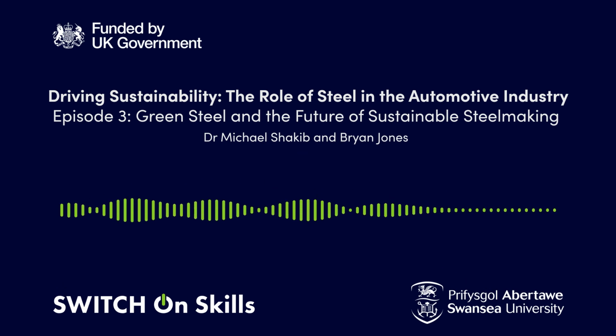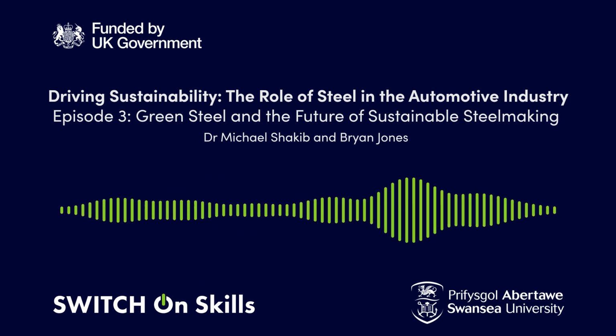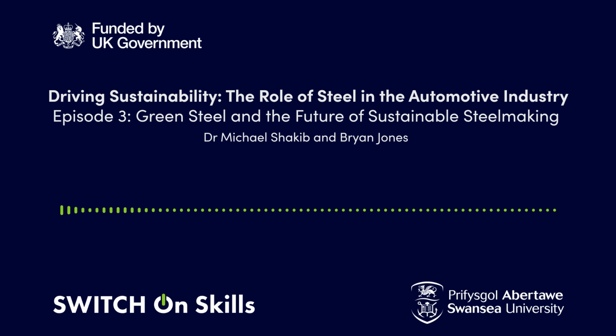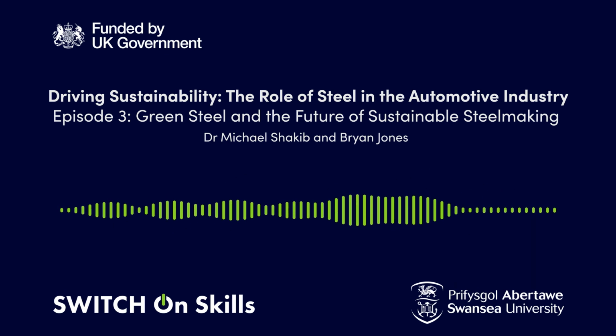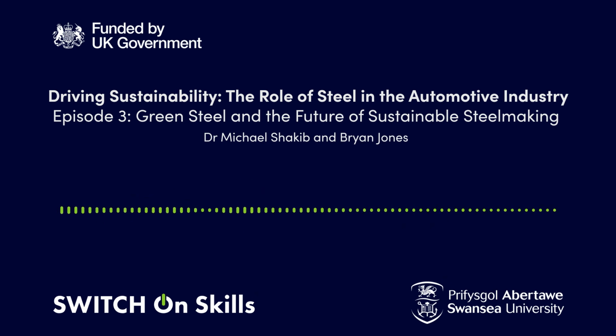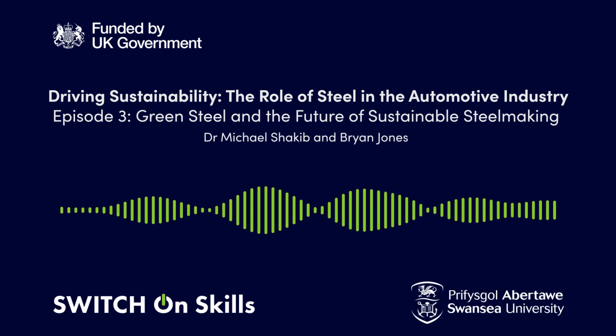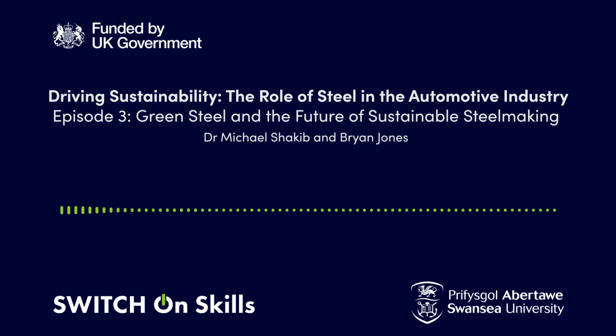And during this process, you can add the other alloying elements to the steel in this vacuum area. By doing this, there's a much more efficient transfer of alloying elements to the product, so that there's no loss of alloying elements. Whereas if you applied these alloying elements during the BOS steelmaking route, for example, then you would lose a certain amount of these very expensive alloying elements in many cases into the slag.